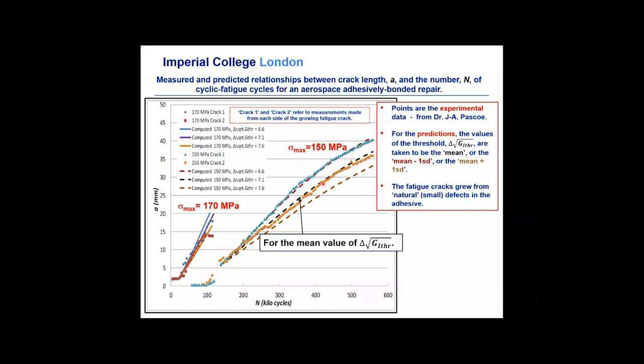And here's our theoretical predictions. This is for the mean value of our threshold. And here's the value -1 standard deviation, and here's +1 standard deviation. So we've got mean and 1 standard deviation either side, which we obtained from the short-term fracture mechanics test. Now we can do long-term predictions. As you can see, the theoretical predictions agree with experiments very well. They capture the data extremely well. There actually are no fudge factors, empirical factors at all in this. It either fits or it doesn't. As you can see, it fits quite well.